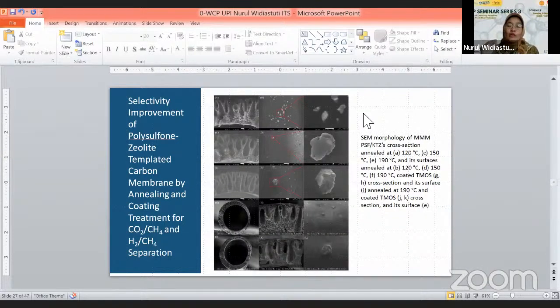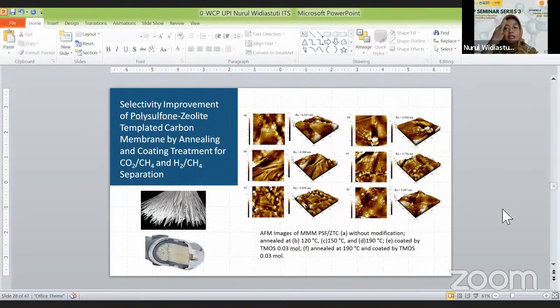To avoid or reduce the voids of the membranes at the interface between the polymers and the fillers themselves. And this is the SEM result showing that at certain conditions, the void from the interface between the polymer matrix and the fillers is already reduced compared to before the modification. And this is the result for the topography using AFM, and we can see that annealed at 190 degrees Celsius and coated by TMOS at 0.03 moles, the surface of the membranes gets smoother compared to other membranes at various treatments here.